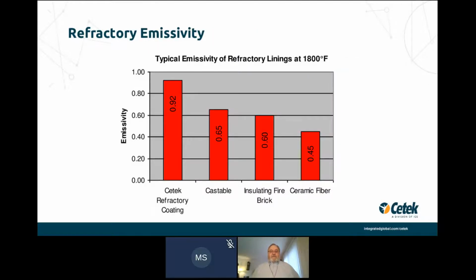This is just a chart showing the emissivities of various refractory materials. Starting from the right-hand side, you can see ceramic fiber, 0.45. Insulating brick and castables are around 0.6, 0.65. And the Cetek refractory coatings are around 0.92.